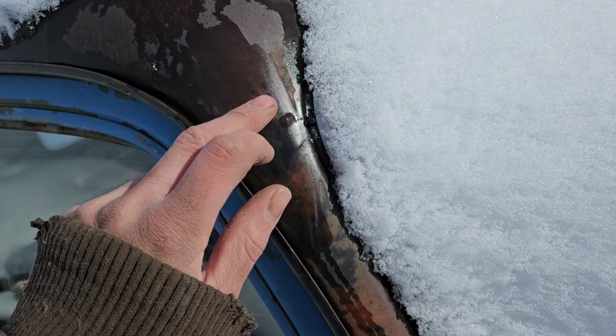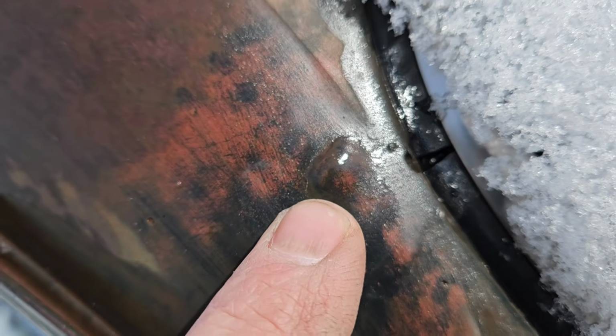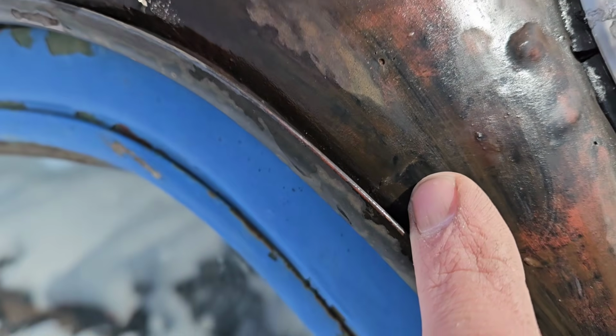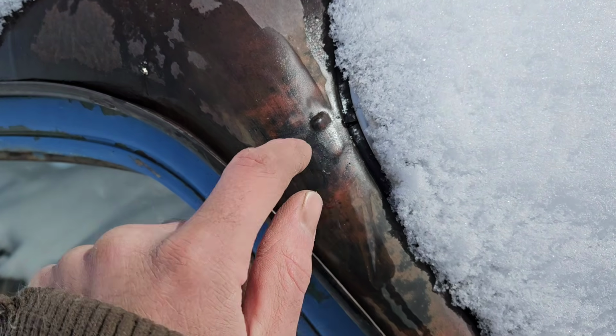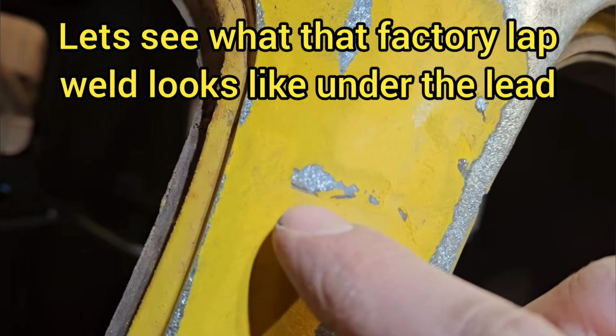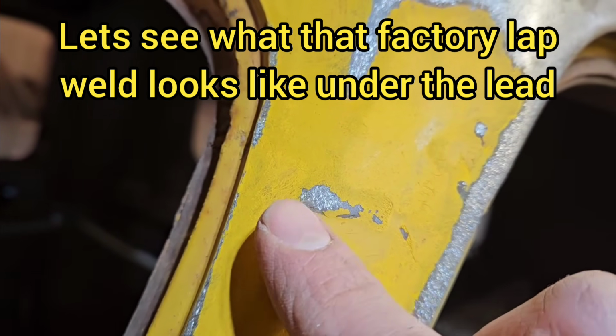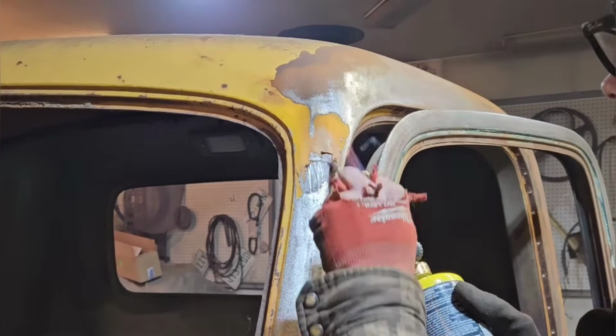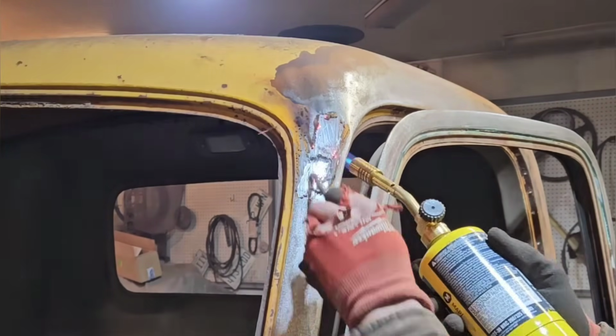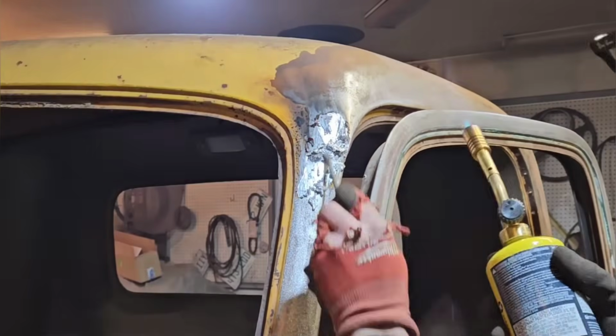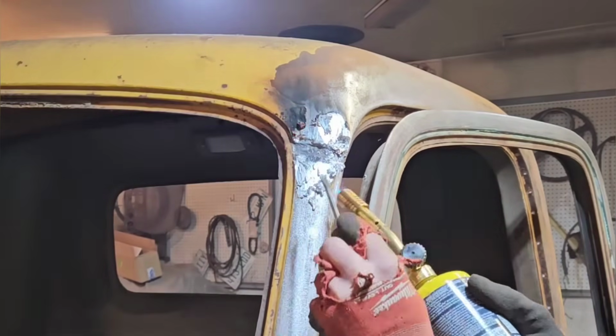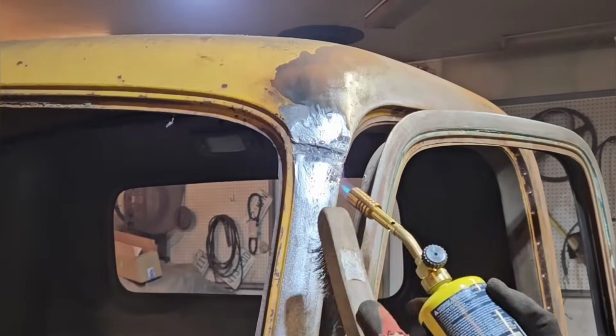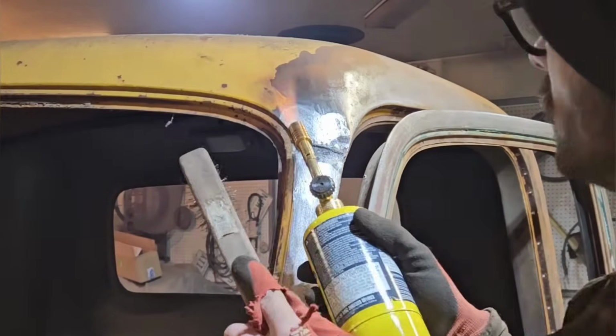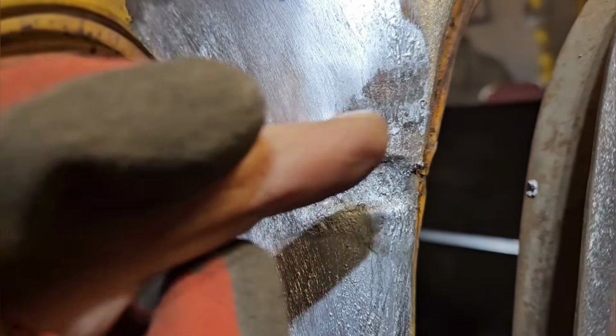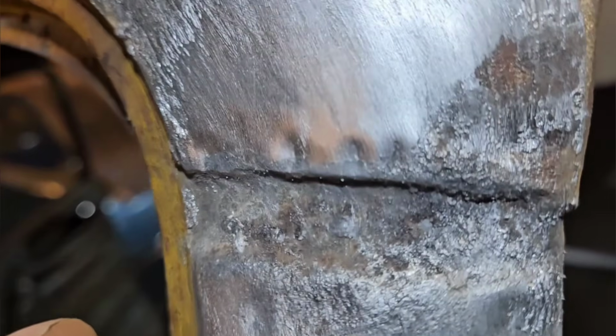This has been lap welded, beaten down, and filled with lead. And we can see that the lead is starting to bubble up and lift, and it's cracking. So there is rust under this seam. The seam has failed. That crack there, you can see that, means that it is rusting out underneath the lead. There's a lot of rust under here. This is where the crack was, and you can see all the rust there.